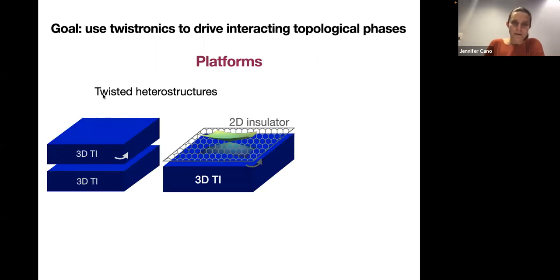So I have a few different platforms in mind to achieve this goal. I'll introduce them in order from least accessible to most accessible. First, we were thinking of these different types of twisted heterostructures. My first idea was, why don't we take two different 3D TIs, these are 3D slabs, say, stack them on top of each other and arrange those with a twist angle. So we're making a 3D version of twisted bilayer graphene, but out of, say, bismuth selenide.